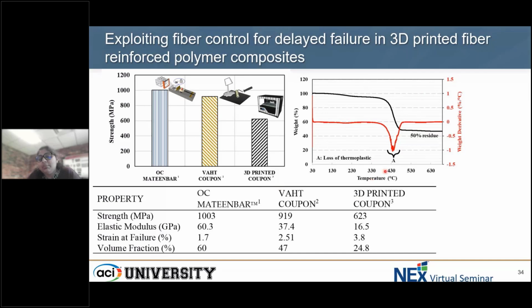Right now, the fiberglass filament has only about 50% fiber, so 50% is fiber and 50% is thermoplastic. Completely adjusting to even 75% or 70% fiber will definitely achieve those strengths that we are not able to see right now. So if 3D printing technology goes in the direction of getting these numbers adjusted to have a higher fiber volume fraction in the filament, we will definitely see some improvements in these numbers as well as the designs that we just saw. So the strength will surely improve.